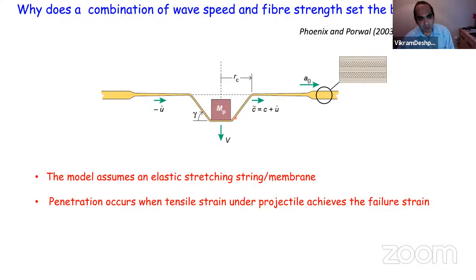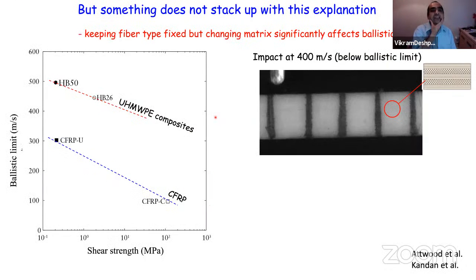And of course, how much it will stop depends upon how much energy can be absorbed. And hence, approximately, I'm saying that why that parameter works is that you need both high wave speed and high energy absorption to stop this. High wave speed to engage more material, and high energy absorption to absorb the energy. But now if you go and do an experiment, something doesn't seem to stack up in this case, because there is no mention of shear strength of the composite in this whole story, right?